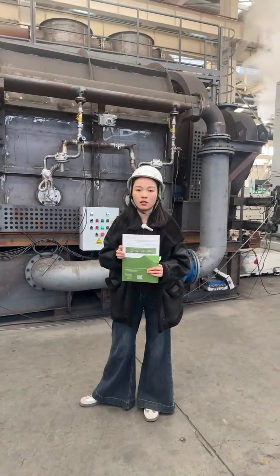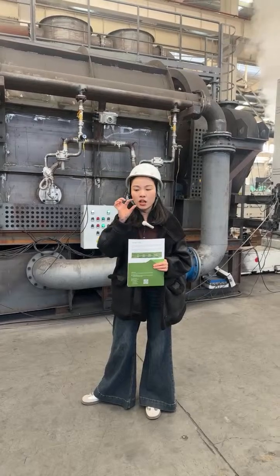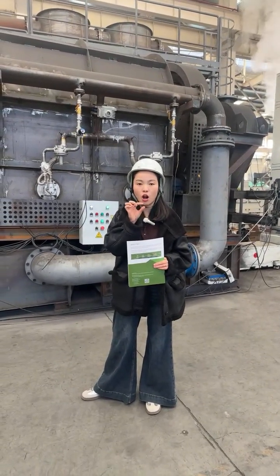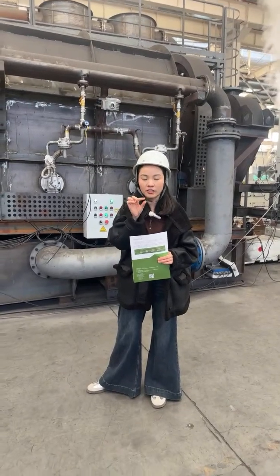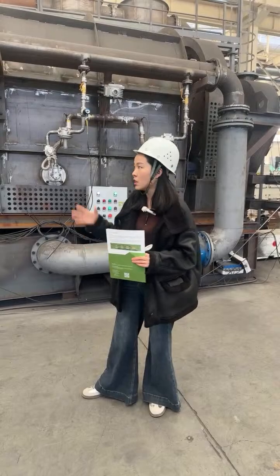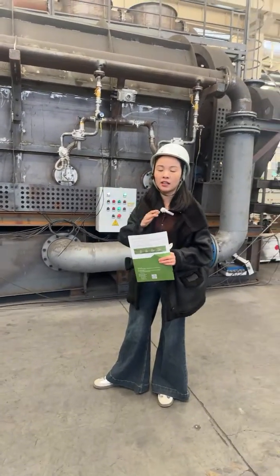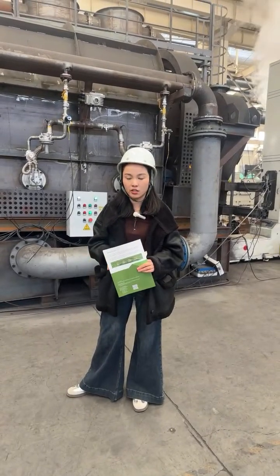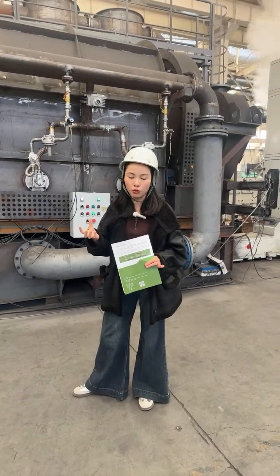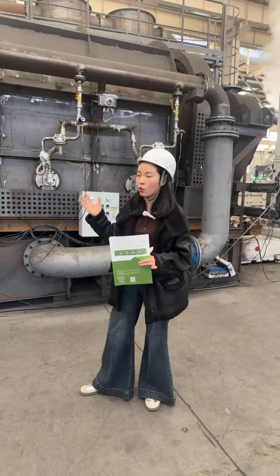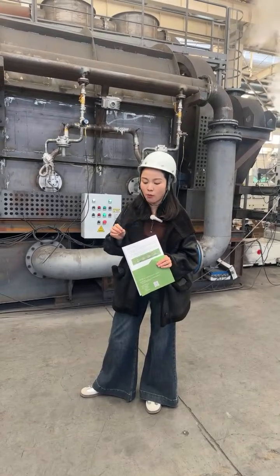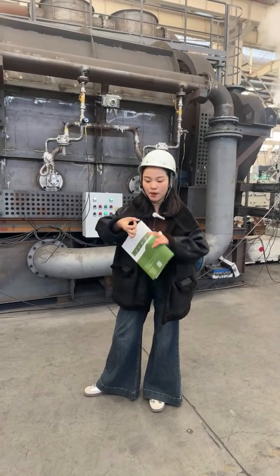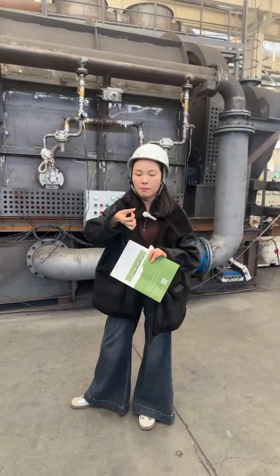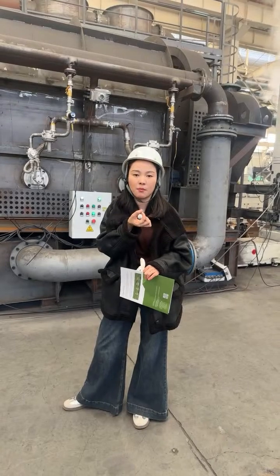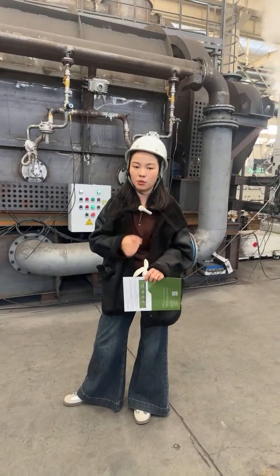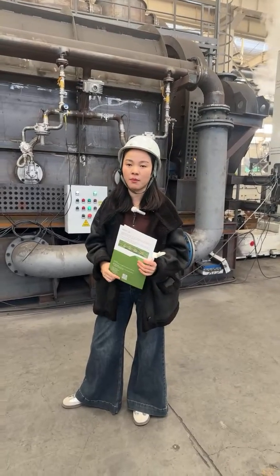And the second reason: there is a chemical binder between the black mass and the aluminum and copper sheet. The black mass sticks on the copper and the aluminum because of this chemical binder. Inside the furnace, the chemical binder will be carbonized and become invalid. So the black mass can be very easily removed from the copper and the aluminum. In this way, we don't have to crush the aluminum and copper into very fine powder. Before that step, the battery is still in 3 to 5 big pieces, but we can get around 90% of the black mass from the copper sheet and the aluminum sheet. In this way, we can get a very high purity black mass.